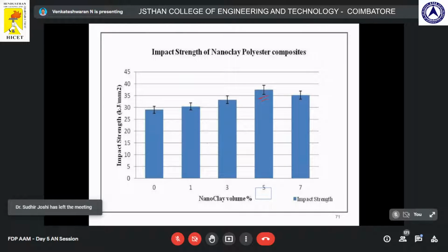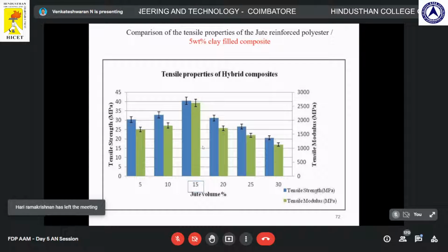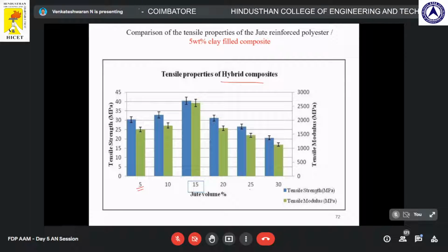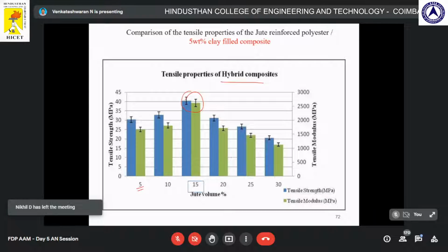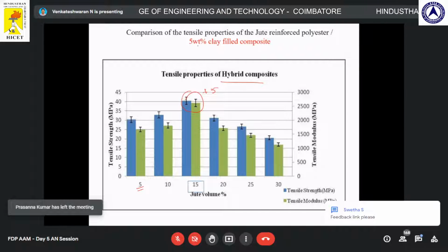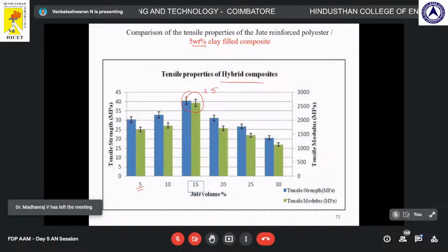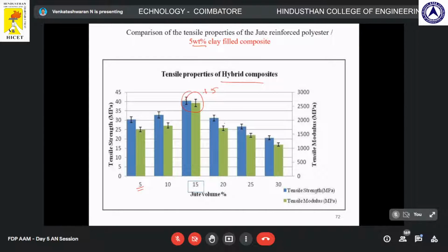So I will take this 5% weight of the nano clay as the better property, and this will be added with the jute fibers to produce a hybrid composite. By varying the jute fiber as 5, 10, 15, 20, 25, 30, when my percentage is around 15 volume percentage with 5% of nano clay, both are, sorry, here also volume percentage. With 5 volume percentage of the clay, I am getting better mechanical tensile strength.